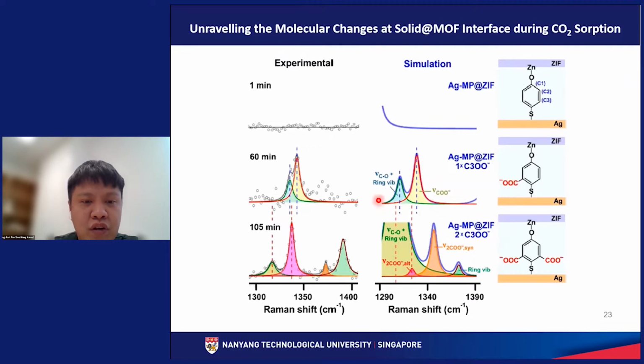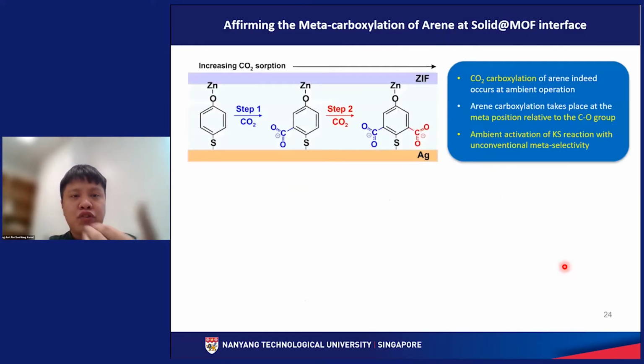So after which, at time equal to 105 minutes, we see 4 peaks in the 1,300 to 1,400 range. So this can be fitted to our simulated data of this particular molecular configuration over here. Okay, so in this case, there is a subsequent or sequential carboxylation reaction also at a meta position. Okay, so through the experimental and DFT simulated results, we can see that increasing CO2 absorption will cause the carboxylation reaction at the meta position. So continuously flowing carbon dioxide, or continuously absorbing carbon dioxide, will subsequently drive the second carboxylation reaction